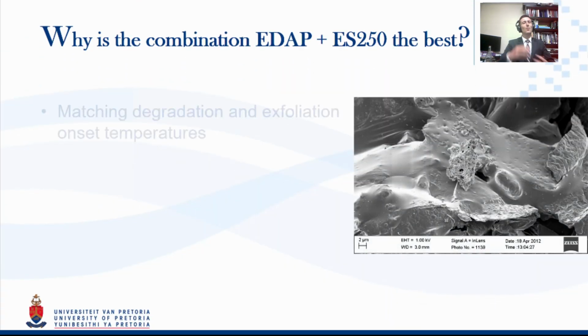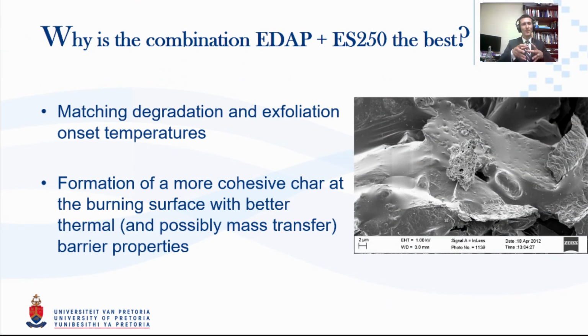So now the question was, why is this combination so good? And that is because once we looked at the TGA, once we looked at a lot of our other results, the thermal analysis results, we noticed that there was a very, very close match between the degradation and the exfoliation events of the two materials. Together they created a very cohesive char as it covered the expandable graphite surface, which then reinforced its previous abilities as a thermal shielding barrier, and then possibly actually reduced mass loss even further because of that coating. And that is why we believe we achieved that synergism.